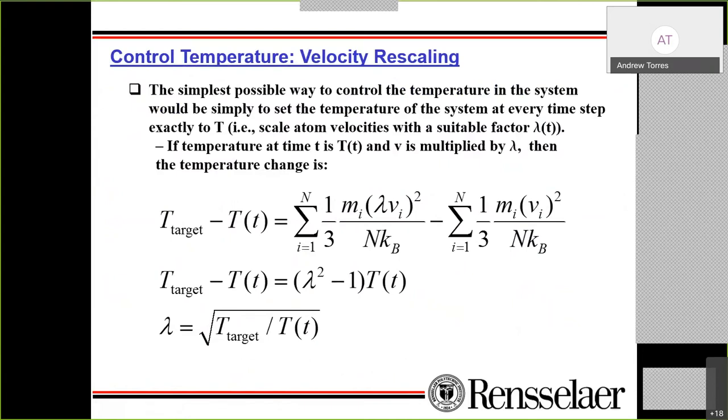When you talked about the canonical ensemble, where you had the quick velocity adjustment to fix the temperature, how do you add in the grand canonical, where you have the particle bath? Right, we can definitely do that. For the grand canonical, usually we couple with a Monte Carlo step. Basically a grand canonical Monte Carlo: given the input chemical potential, once you insert a particle, we compute the chemical potential change, and then we throw the dice and accept it or not, right? So for MD simulation in the case of the grand canonical ensemble, we have to couple an MC step to it, so it is possible. Okay, I see.